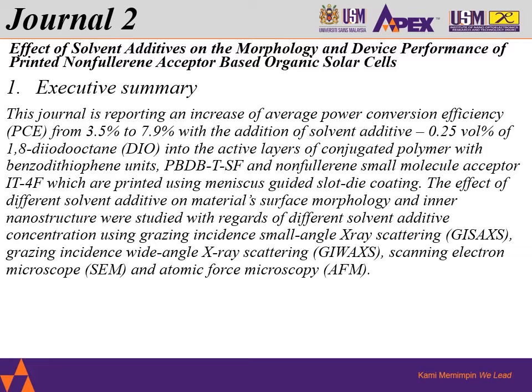And these are printed using meniscus guided slot die coating. So the effect of different solvent additives on material surface morphology and inner nanostructure were studied with regard to different solvent additive concentrations using GISAXS, GIWAXS, SEM, and AFM.